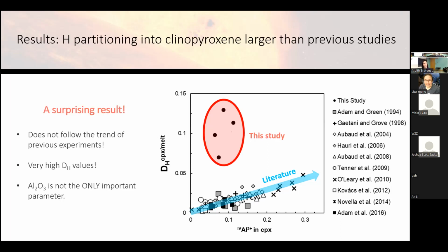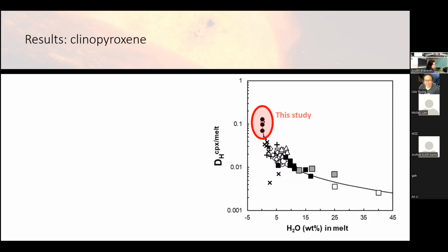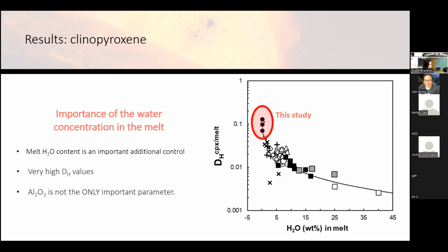But you can probably guess why, considering what I first told you about these samples. But essentially, they have extremely high partition coefficients. The reason why is because solubility is not the only determining factor. The partition coefficient, of course, is a ratio between the mineral and the melt. And if you have a melt that's very, very low in water content, that's going to create a much higher value for the entire partition coefficient.